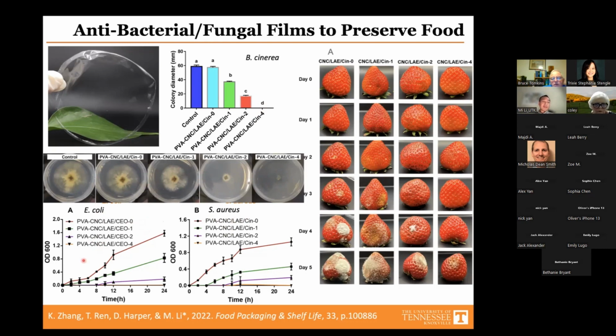And we did pretty much the same thing, with a control, and 1%, 2%, and 4%. And then we measure the OD, the density of the bacteria. For the non-added control right here, the bacteria grows pretty well. In comparison with the control, the 1% has a pretty obvious drop of the growth. And for 2% is a significant drop, and 4% is completely inhibited. And the same thing for the other strain, the S. aureus bacteria, and it also shows a very good inhibitory function.